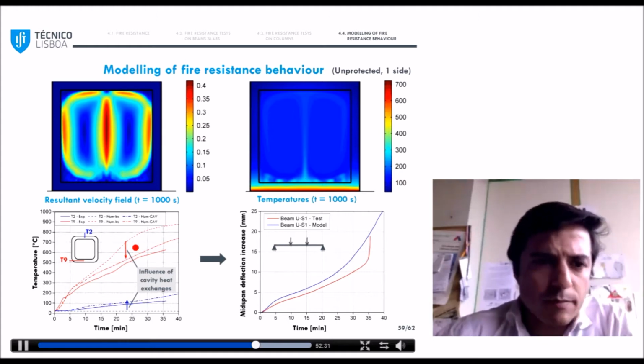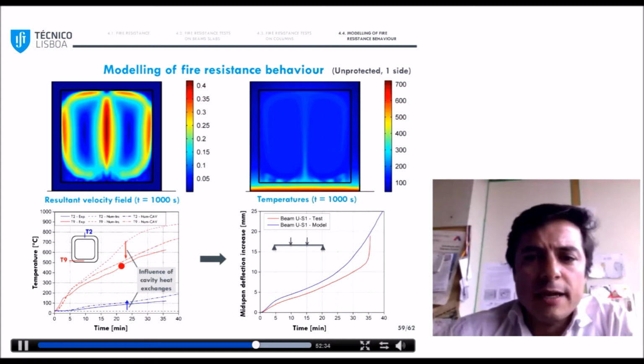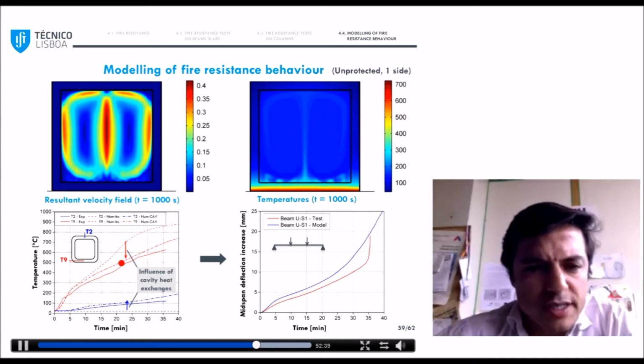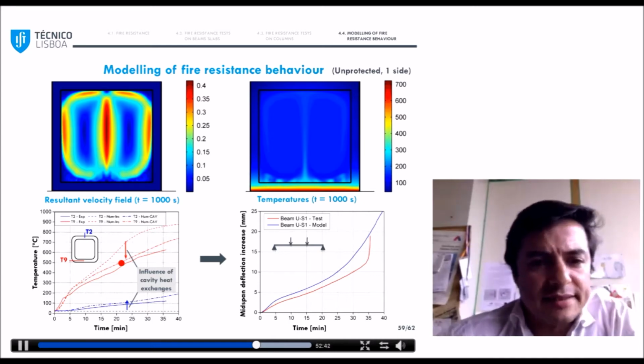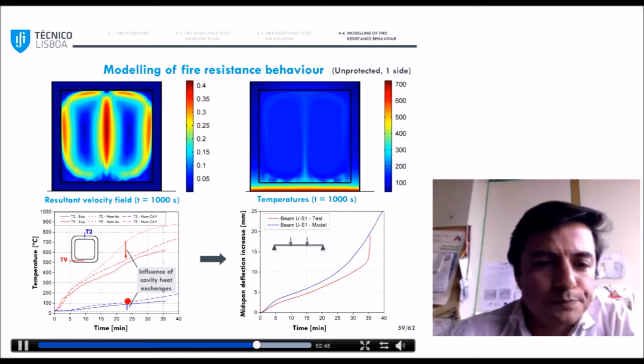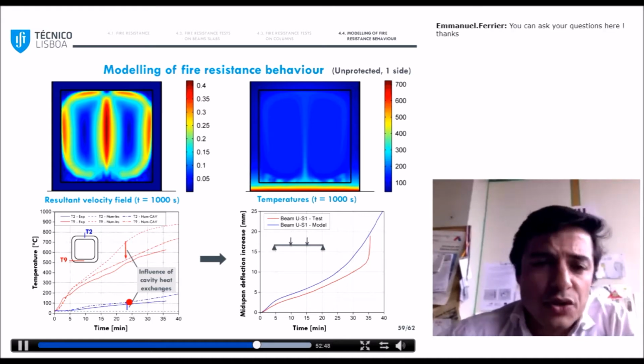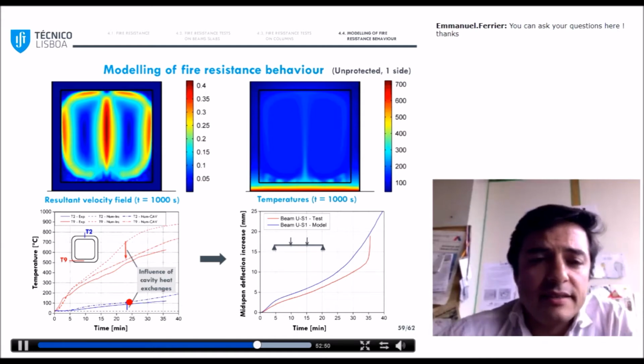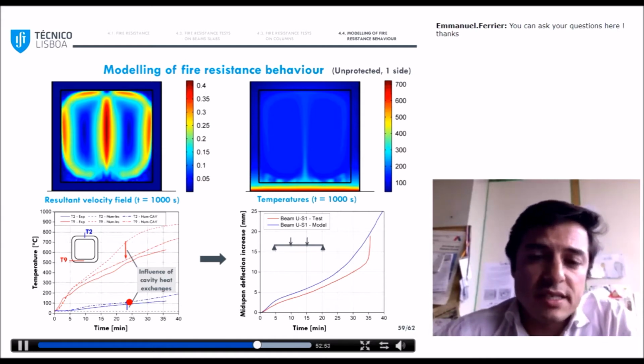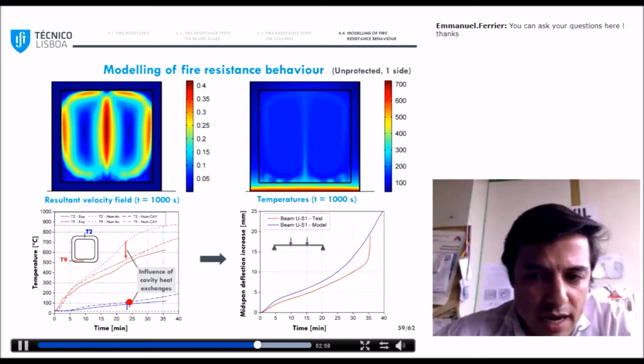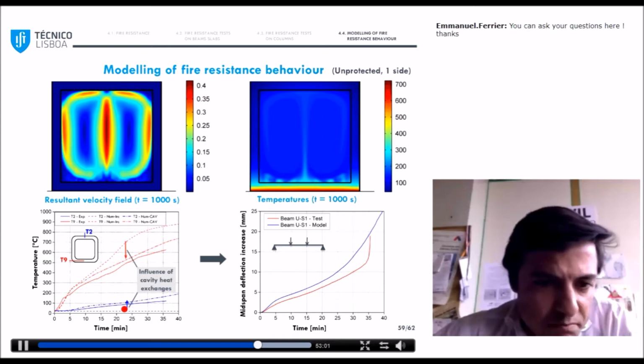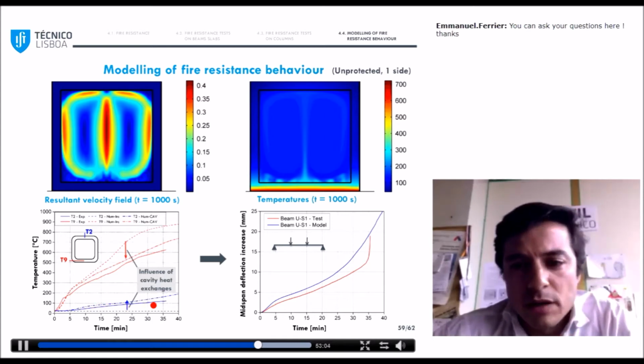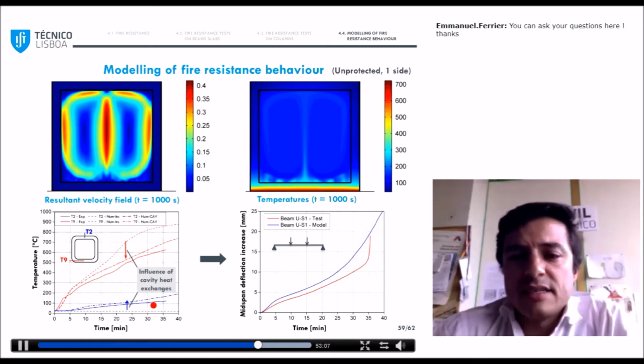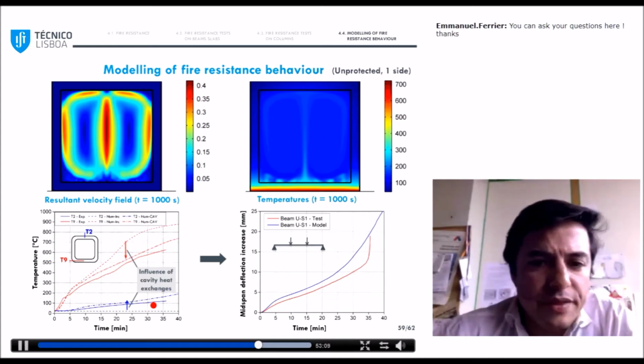In your bottom left picture, you can see comparison between experimental and numerical temperatures. In red at the center of the bottom flange, and in blue at the center of the top flange. So here the main point is that the cavity heat exchanges are very relevant. So for instance, if you do not take them into account, the bottom flange basically does not heat in the numerical model. So by incorporating these effects, we obtained a much better agreement with the experimental data.